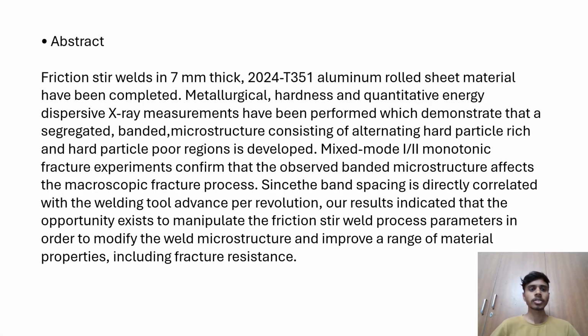First, abstract. Friction stir welds in 7 millimeter thick 2024 T351 aluminum rolled sheet material have been completed. Metallurgical, hardness and energy dispersive X-ray measurements have been performed, which demonstrate that a segregated banded microstructure consisting of alternating hard particle rich and hard particle poor regions is developed. Mixed mode monotonic fracture experiments confirm that the observed banded microstructure affects the macroscopic fracture process.